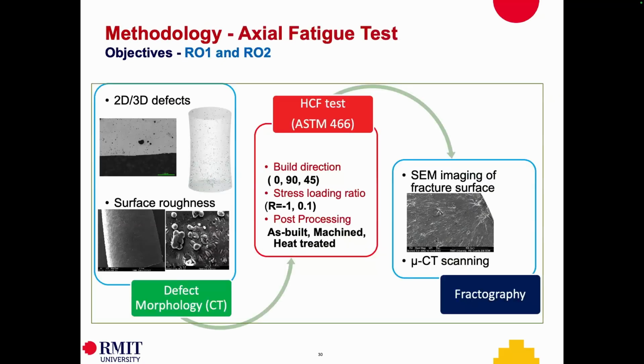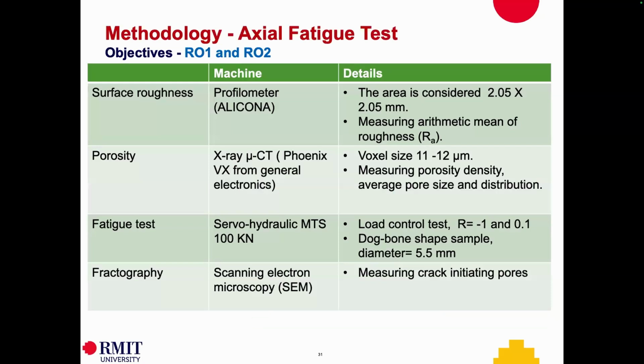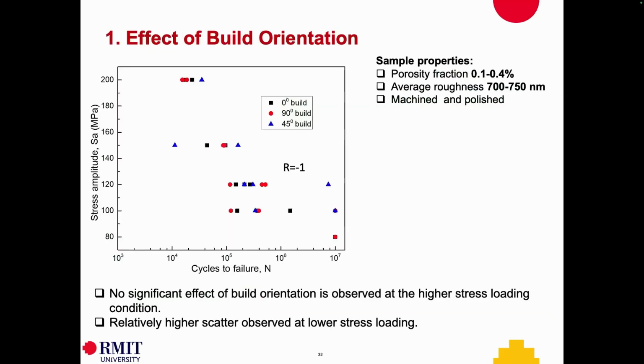So basically, we looked at 2D and 3D defects with CT and SEM, looked at the surface roughness with a profilometer, and used a series of build directions, 0, 90, 45, two different load ratios, completely reversed and positive loading, and we looked at as-built, machined, and heat-treated conditions. And we did detailed SEM scanning of the material. These are the different equipment we used. And let's talk about what we see in the build orientation.